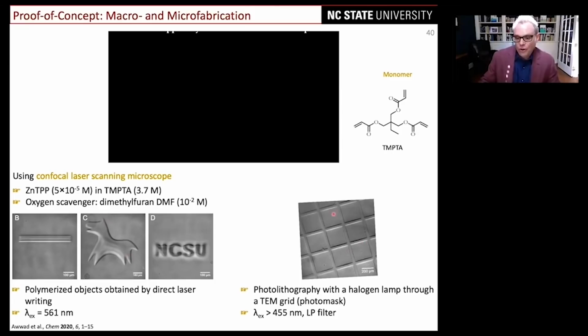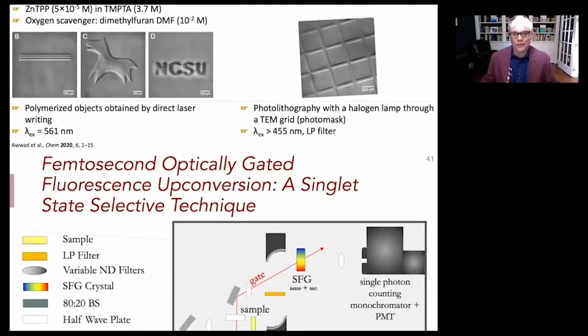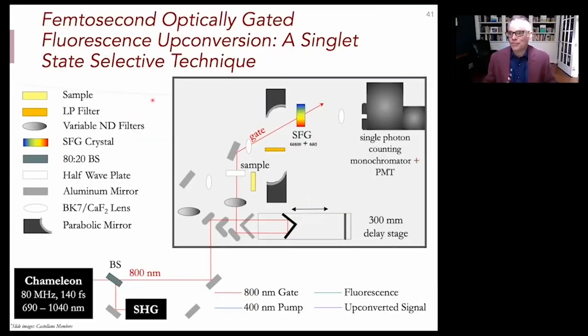And we can do photolithography as well. This is through a TEM grid. So the idea is that with TMPTA, which is a cross-linking monomer, which is also a pure solvent, you can basically do ultra-fast quenching of the excited state of the S2 in the porphyrin. But how do we know we do that? And you knew I wouldn't leave it there. I'd have to show you, how do we know it's the S2 quenching by electron transfer?